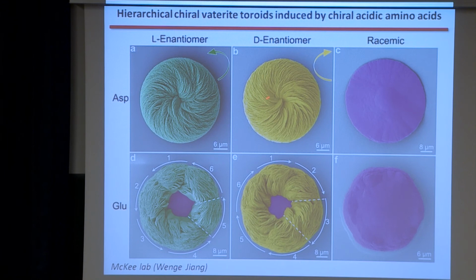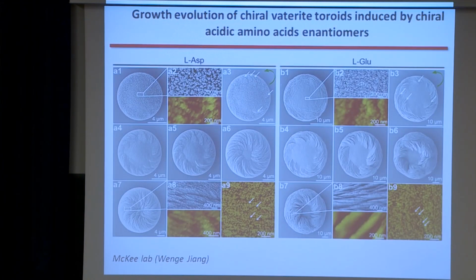Asp gave these very nice discoids. Glu gave similar chirality, but with 6 hexagonal subunits in this kind of toroid formation. A racemic mixture, 50-50 of the 2 amino acids, gives you a more typical achiral vaterite disc. We looked at the evolution of growth of these discs and toroids. You first get an amorphous calcium carbonate disc made of all these nanoparticles, here by SEM and AFM. The platelets, for some reason, start to form at the edge. We're trying to work it out. This is Asp and this is Glu on this side.